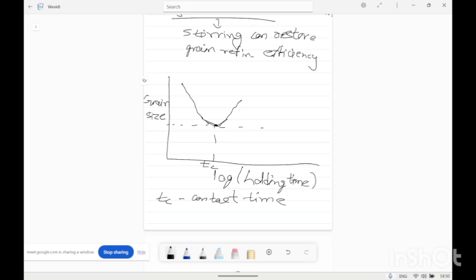So this effect is due to fading. If the melt is stirred, the grain size will again start to decrease and increase after some time. So this recovery in grain refinement efficiency is done by stirring. At this point of time, when stirring is done, the grain refinement will start to recover.